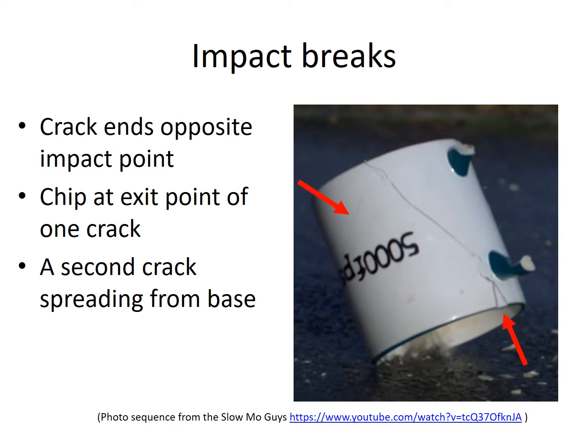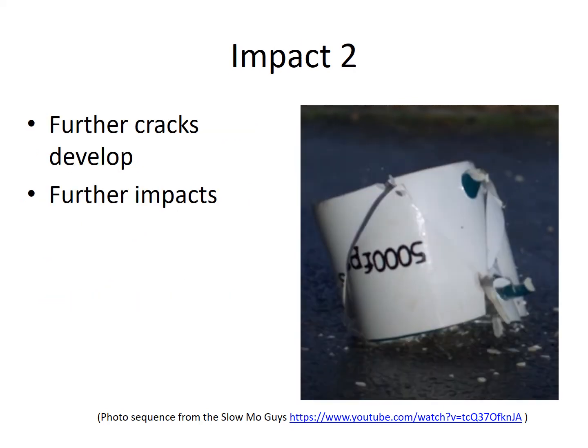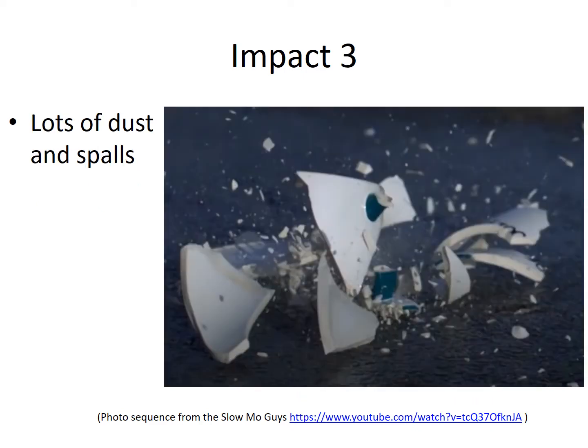So here we can see one side of the mug's rim hitting a hard surface with force. The impact creates a crack which runs rapidly around the mug, exiting the rim on the other side, forcing a chip off as it does. As the crack meets the join between the base and the wall of the mug, the crack propagates. As the impact continues, the cracks propagate further. The force of the impact is dissipated by a large amount of shattering and splintering because the mug is hard and rigid.